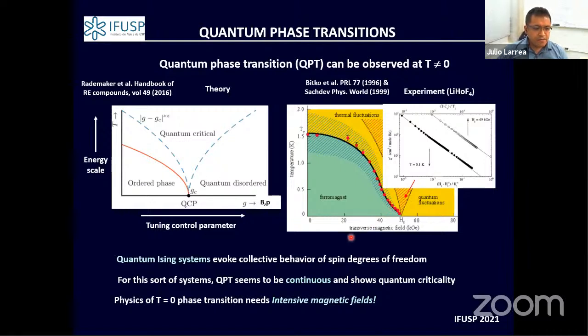So what we learn from this system is that collective behavior emerges as you approach the quantum phase transition in the spin degrees of freedom. This phase transition, which happens at zero temperature, seems to be continuous for this particular case of the quantum Ising model, showing quantum critical behavior.